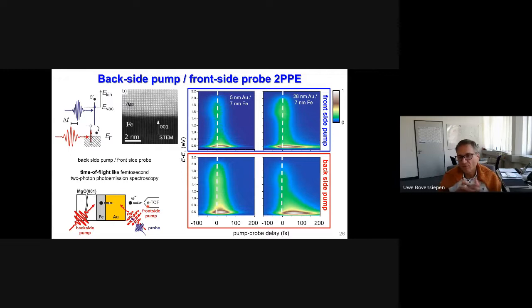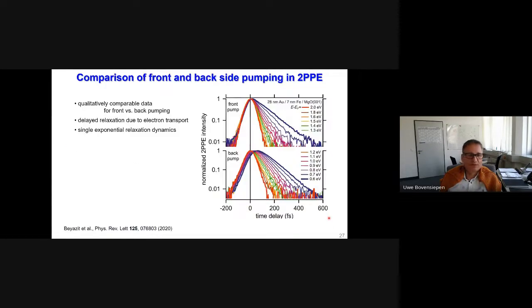Now, first of all, one has to ask the question whether it works well. And I show you here data. This is the energy above the Fermi level. This is pump probe time delay for 2 different gold thicknesses. So 5 nanometer of gold and 7 nanometer of iron, and a thicker gold layer also on iron for the front side pumping and for the back side pumping. This color scale is the intensity, and you basically see both geometries work pretty well, and we can really exploit this in quantitative experiments.